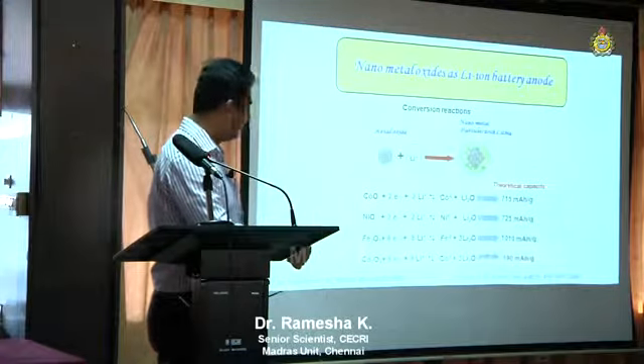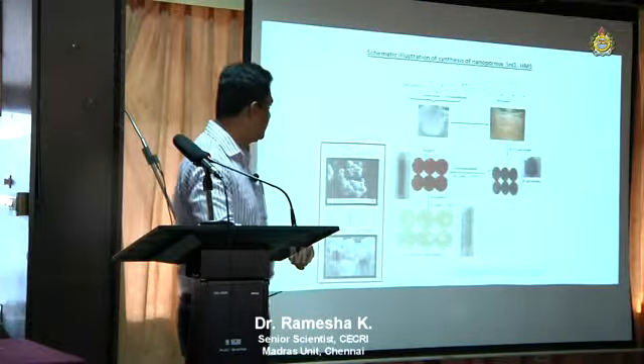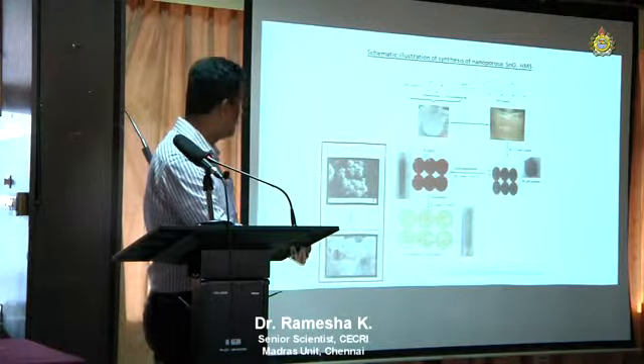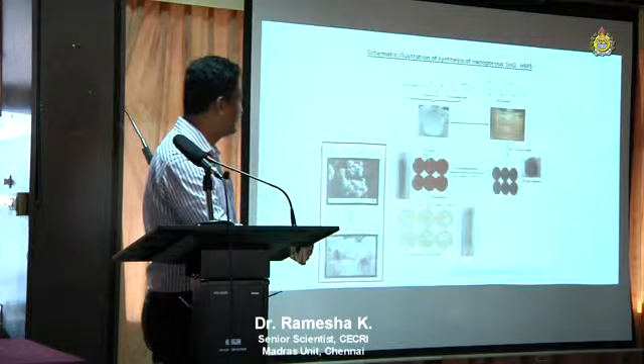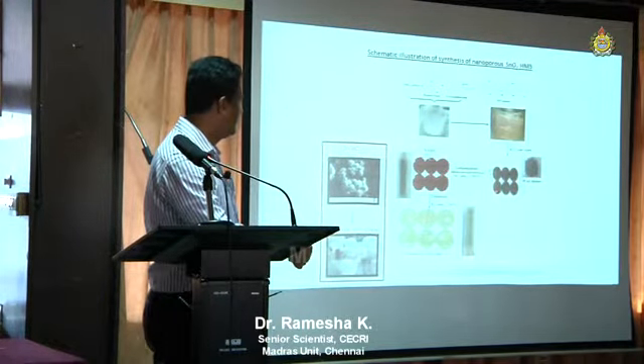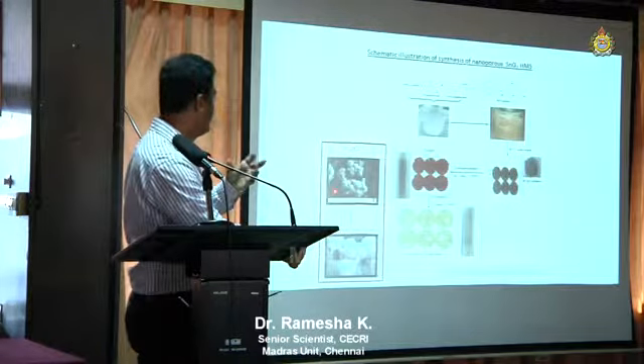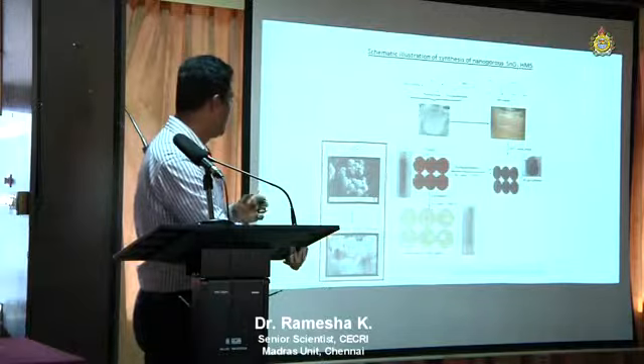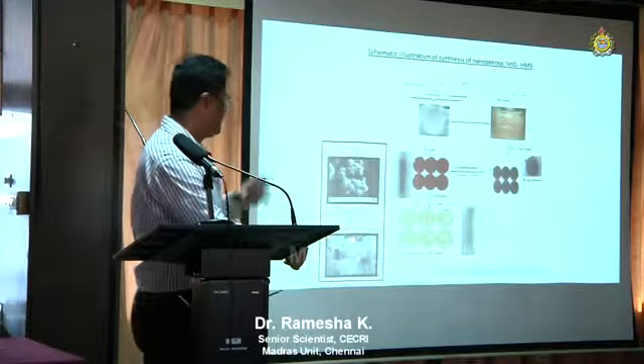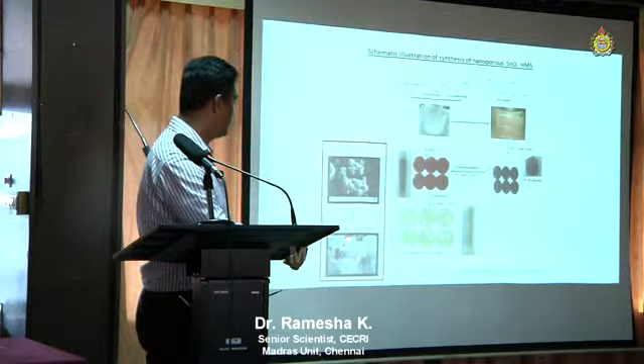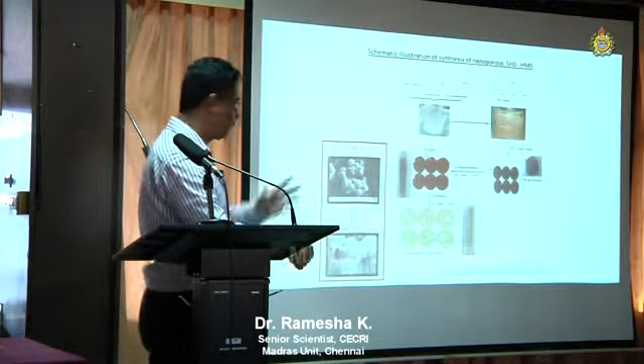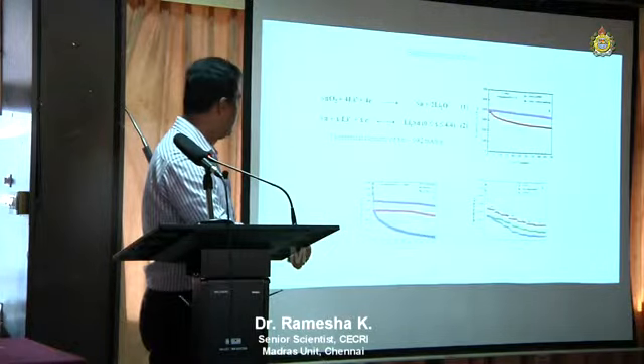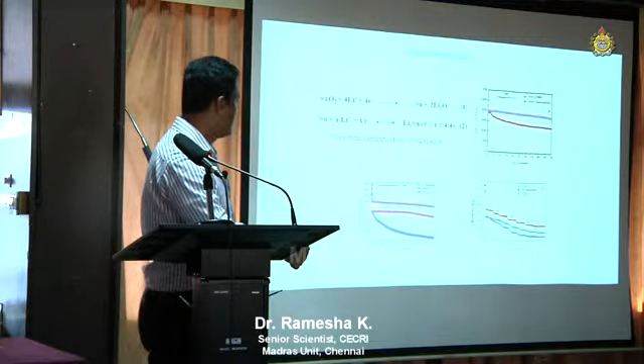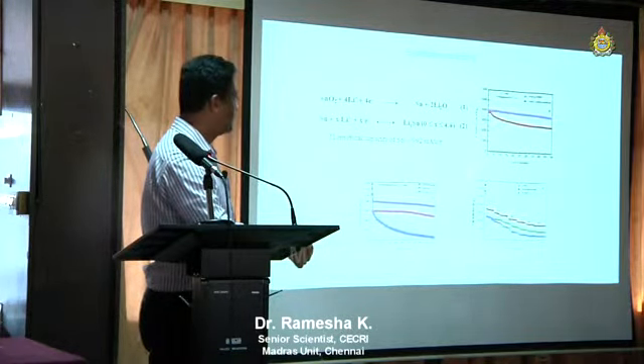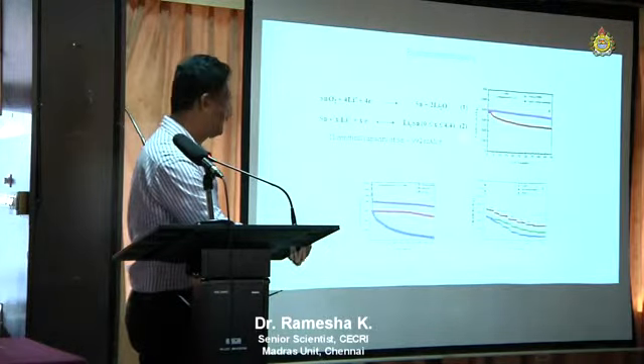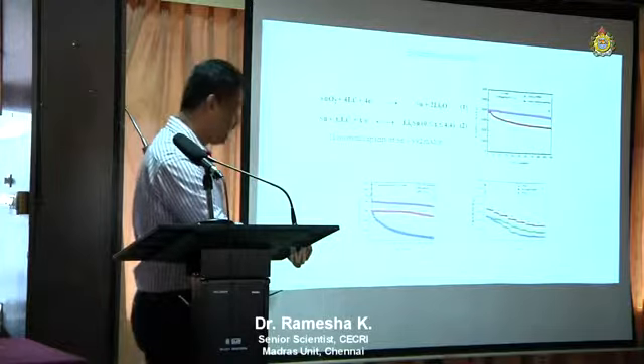Again, the issue is that you are making them nano. We have made nanoparticles of tin dioxide, SnO2. Starting from tin chloride, we use a polymerizing agent, a carbon coating agent, polymerize, heat it, burn it. Finally, you get a highly porous, hollow tin oxide, SnO2 particles. It is hollow inside, so all the tin oxide is on the surface, like a football, right? When we use that, we can get a capacity of 800 continuously for many cycles. If you don't use nano, within a few cycles the battery is dead.